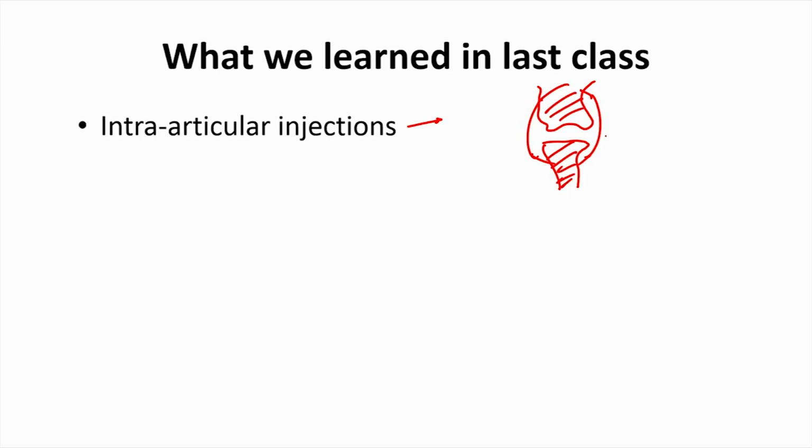What we also learned is this synovial membrane contains lots of blood vessels and lymphatics, and they can clear out things very rapidly if they are smaller in size. So, if you want to inject something to reside for long durations, you want to inject bigger particles that can release drugs, or the drugs itself may be big. Anywhere above 1 micron would start to give a much higher residence time than anything below that.